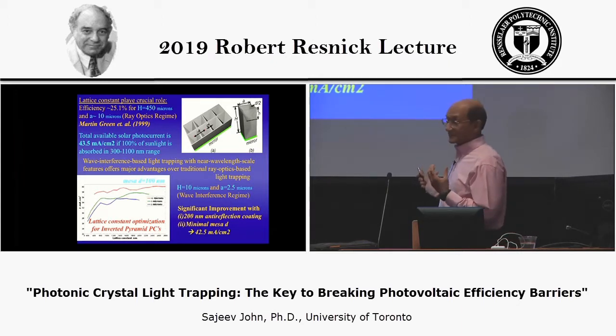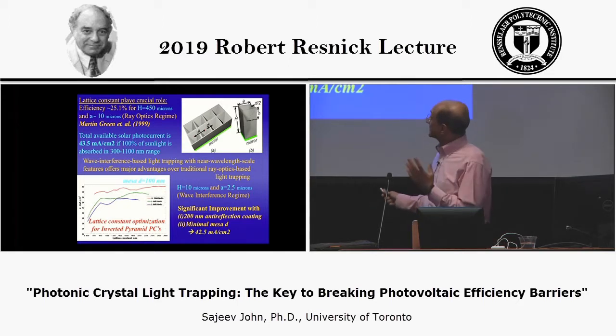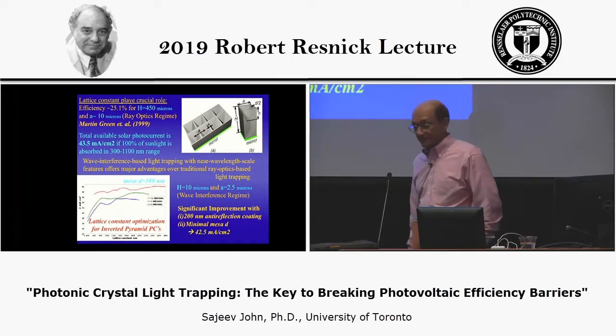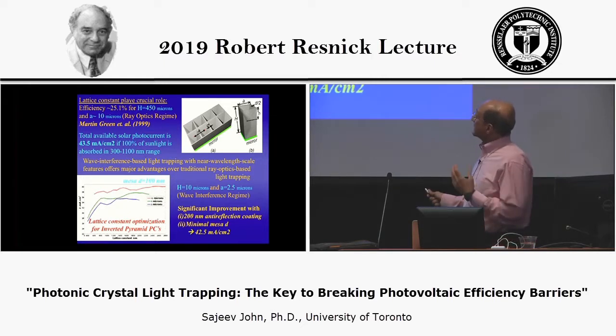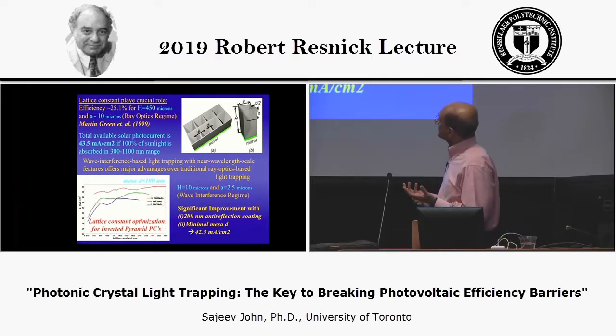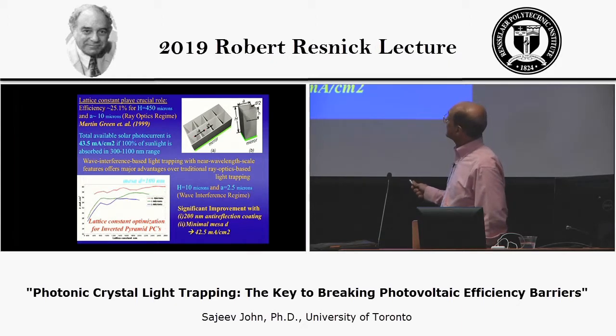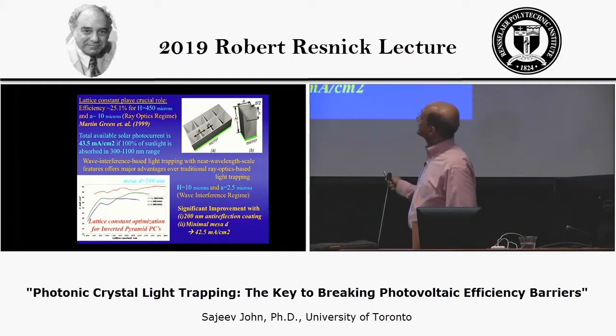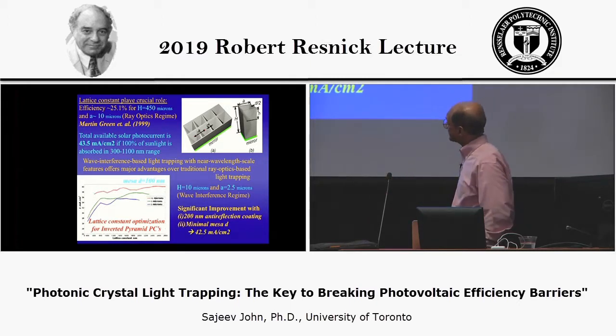Inverted pyramids have been considered quite a long time in photovoltaics, going back to early work of famous scientist Martin Green back in the late 90s. He, again, was thinking in terms of ray optics, so he considered a lattice constant which is close to 10 microns, which is much longer than the wavelength of visible or near-infrared light. And this led to a world record efficiency of about 25.1% back in 1999. So you can see that the efficiency hasn't gone up a lot since that time, and the thickness of the structure that he used was about 450 microns of silicon.